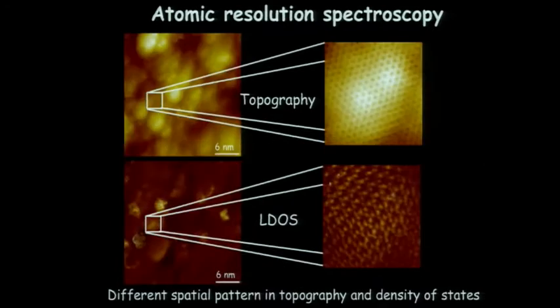But really with the STM, we can also combine these two modes together. We can take this topographic mode and do the spectroscopy at every position, and that gives us information on a spatial map of the local density of states. What you see here in the top image is the topography, where the atoms are actually sitting. If we zoom in here and look at the density of states of the sample, it also has some periodic modulation to it.